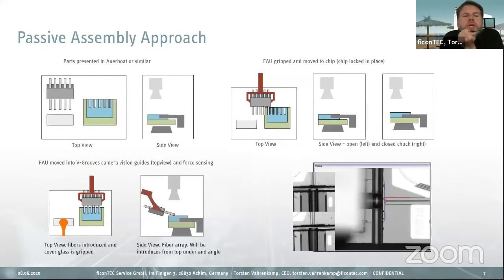If you see the passive approach, as an input you have the fiber array, you have your chip with V-grooves, and you have a cover glass. When you go into the machine, you need to plug in the chip, lock it down in place, and bring the fiber array to the V-grooves. Then you need to slide the fiber into the V-grooves, very gently, and monitor the fibers while you let them glide into the V-groove. While you do that, you monitor the back reflection from the surface of the fiber, and by looking at the reflection you see if the fiber has nicely entered the V-groove.